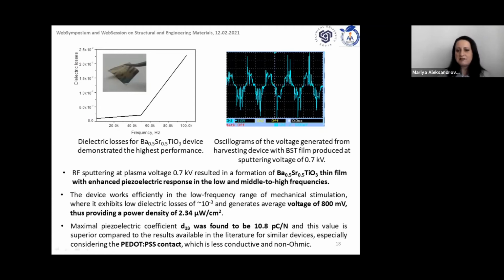However, some spikes in the electrical signal appear that need to be carefully processed by the power conditioning system. They are due to the point contact from the non-uniform dendrite structure of the functional film. But still, satisfactory results were obtained: a voltage of nearly 800 millivolts and an electrical power gain of, let's say, 2.3 microwatts per square centimeter.